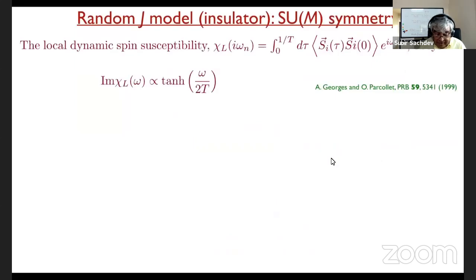All right. So what can we say? Let's measure it in terms of things you might measure with neutron scattering if you had some kind of random spin system. Let's measure the local dynamic spin susceptibility. Well, the Fourier transform of d tau over tau gives you a log, but when you take the imaginary part, that just gives you a step function at the origin. And at finite temperature, that step function becomes this tanh. So this is a function that becomes a step function as T goes to 0. So the imaginary part of the susceptibility, which has to be an odd function of omega, has a discontinuity at omega equals 0 at T equals 0.